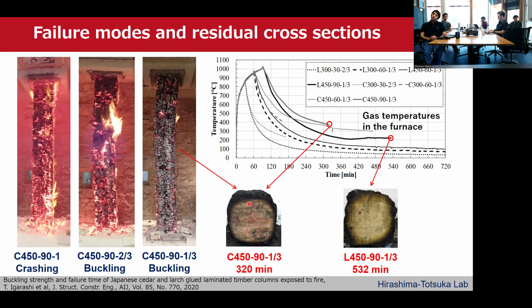This photo shows the residual cross-section of a column with a square cross-section of 450 millimeter after being heated for 90 minutes and left to cool for 230 minutes. The column specimen buckled and failed 320 minutes after ignition. Buckling failure was also determined based on the amount of rotation measured of the column.